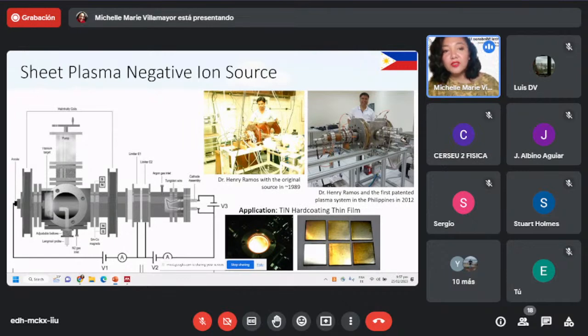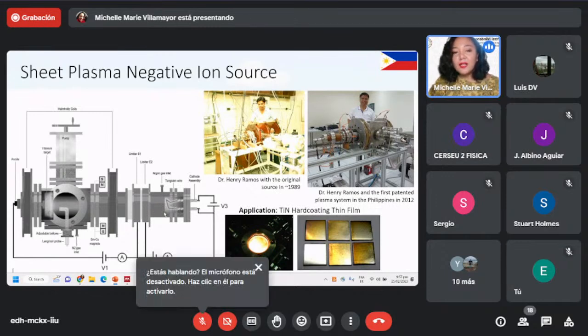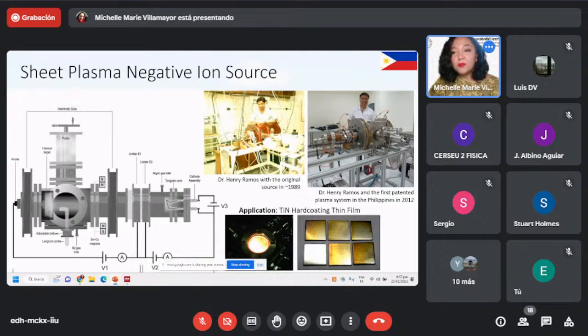And San Miguel Corporation is actually a bottling company. They also produce beer here in the Philippines. And so Dr. Henry Ramos applied for funding to change the glass chamber into an all-metal chamber. And then later on, he was able to commercialize this and double the size of the extraction chamber, which was then used by a company to deposit titanium nitride hard coating thin films. So this was him when he was starting in 1989, and this was him in 2012, almost 11 years ago.